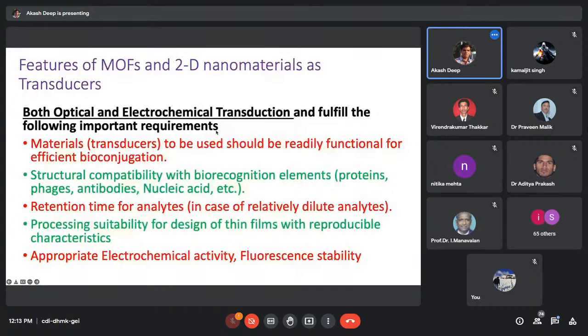Retention time for analytes. Many times, the samples that we want to test contain very low concentrations of analytes, and in such cases we need a retention time so that the sensor remains in contact with the sample for a long time, and allows diffusion into the inner structure. So these are porous materials. The sample can diffuse into the vicinity of those active sites, and because of that, we achieve better sensitivity in the detection. Then processing suitability for the design of thin films with reproducible characteristics.